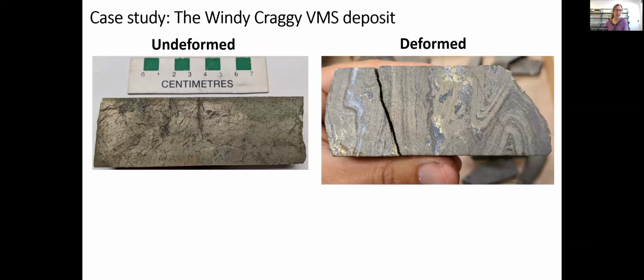So, for example, here we have slices of drill core showing on the left, relatively undeformed massive pyrite, and on the right, a beautifully folded, bedded sulfide assemblage. And this is really nice because the sulfides in these beds like this tend to retain a lot of primary textures, but then you have stuff that's been remobilized, like these coarse grained bits, it's been remobilized into the fold hinges. So we can compare those compositions and see how they change during remobilization.